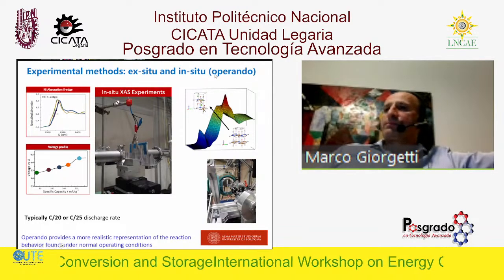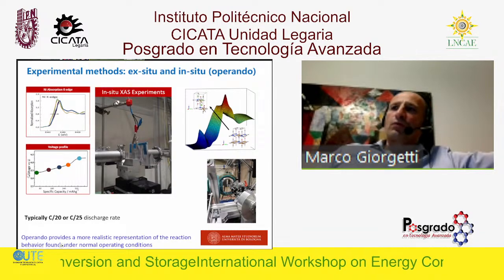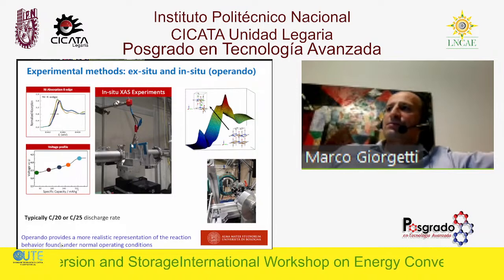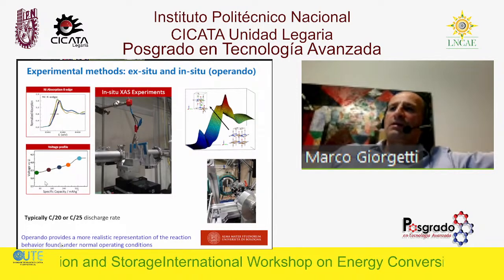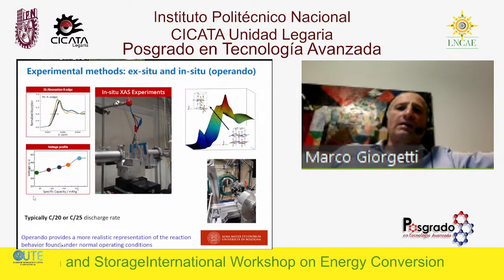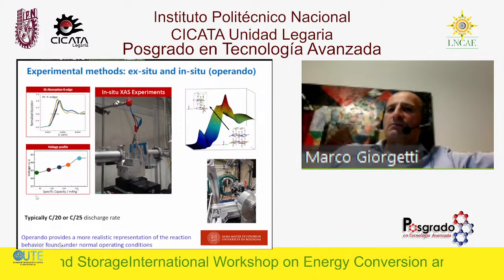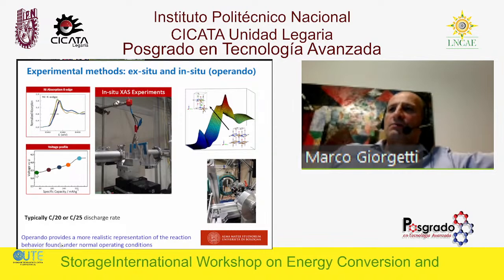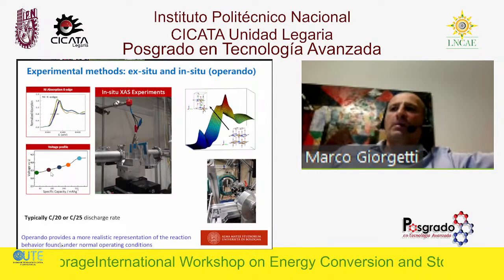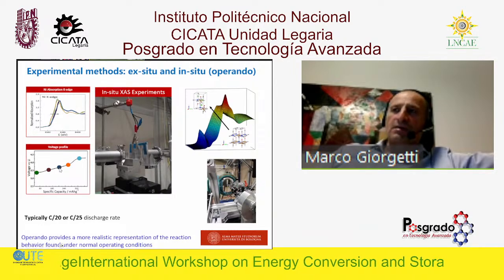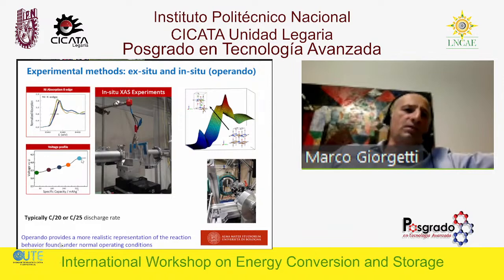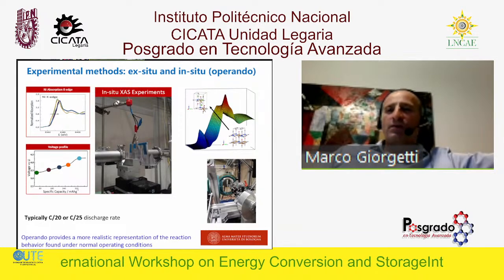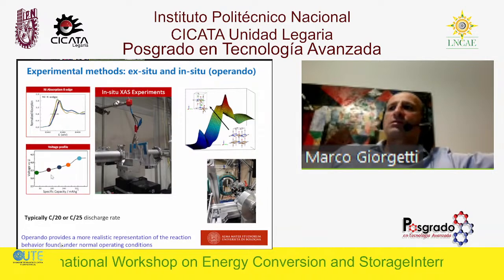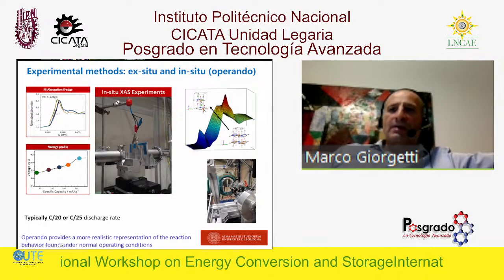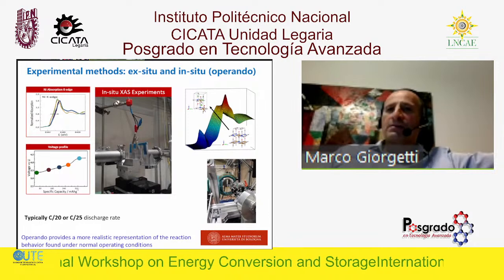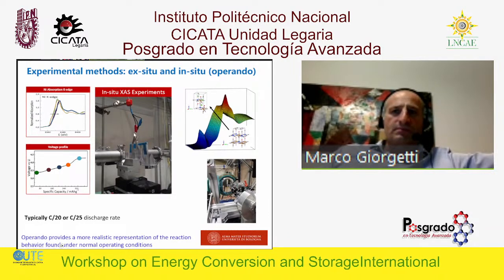In the ex situ modality, of course, you know the voltage profile. This is the charging curve of a battery, a pouch cell that has been connected here with a cable. Ex situ modality means that the experiment is taken just with the electrode material at different states of charge. So I measure this, then I open up the cell, measure this, then another cell, I stop the voltage here, another cell, stop the voltage here. This is something that you can prepare in your lab. Then you go to the synchrotron, and then you have the measurement done. So this is what we call ex situ methods. And operando means that the cell, on the other hand, is connected with a cable to the galvanostat for a charge-discharge cycle.